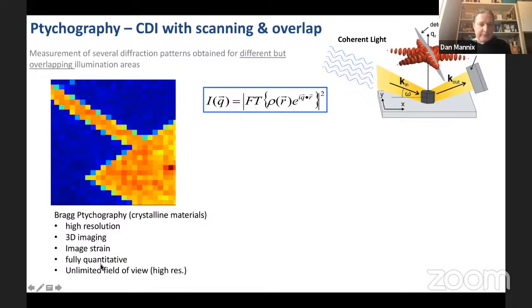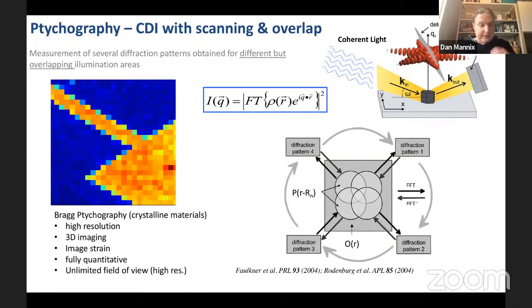It's fully quantitative, and essentially you have an unlimited field of view because you just have to scan your sample around. In practice, that might be more difficult because of time or stability limitations, but in principle that's an unlimited field of view. And given that magnetic domains exist over these long length scales, it's nice to have this large field of view, so that you can zoom in or zoom out to different areas, again with high resolution.